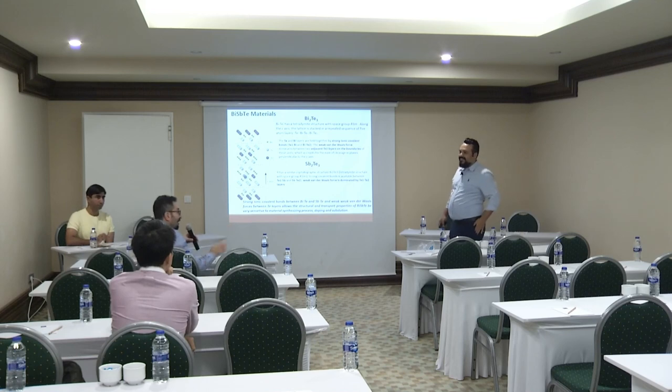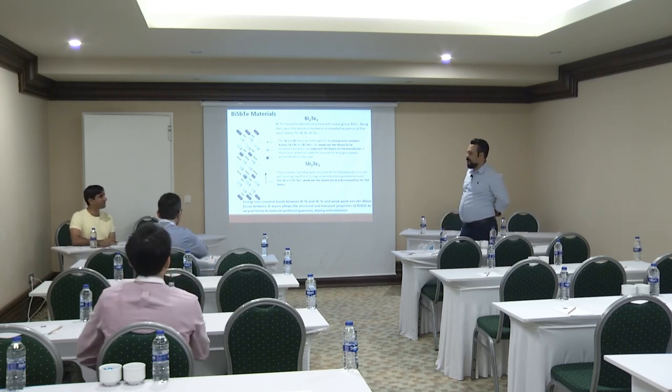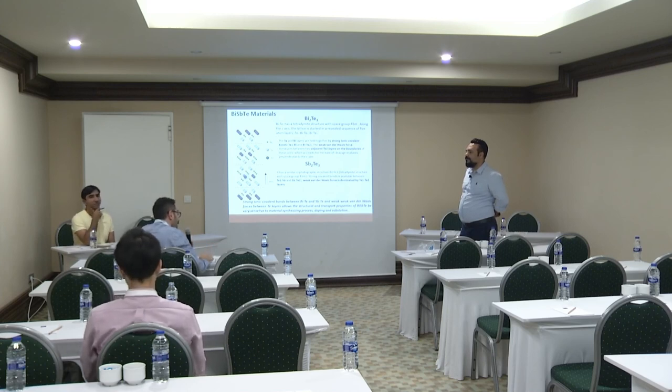Okay, last question. Is there any other question? Just one more question and then I will finish. For bismuth antimony telluride, are you doing SPS or hot pressing at 400 degrees Celsius? Not hot press. We just use sintering, about 400 degrees for 10 hours. But when we do the measurement, we go up to 250 degrees.